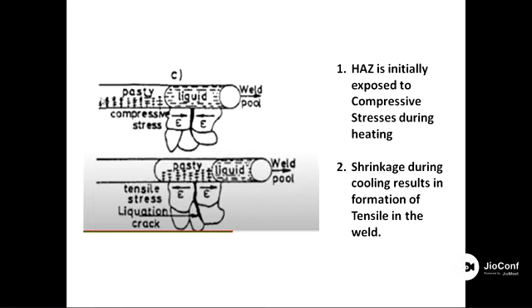This is your weld pool. Now you are progressing from left to right, and immediately after your weld pool there is liquid because it has still not cooled down, and beyond this is a pasty zone. It means it has cooled or is in a semi-solid form. While welding is in progress, the area near the weld pool is under a compressive state because of the heating; the surrounding base metal is compressed because of the expansion. But as the weld progresses, far away from this zone, in the pasty zone, in the semi-solid or under-cooling condition, contraction stresses are developed because of the cooling and tensile stresses are produced.